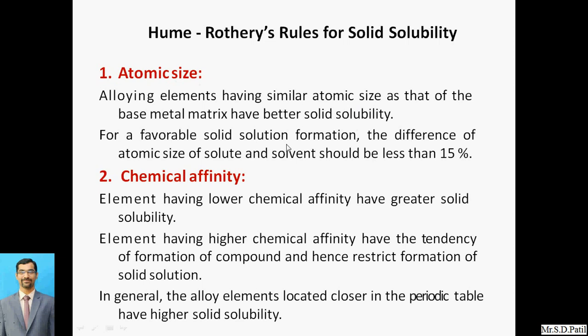So for favorable solid solution formation, the difference in atomic size of solute and solvent should be less than 15%. There may be some minor difference, but that difference in atomic size should be less than 15% to achieve proper solute solubility. Then the next term is chemical affinity.